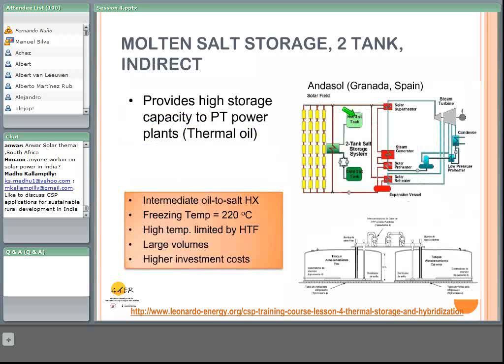You can see that it's a two-tank molten salt storage with a nitrate salt mixture, melting point of 223 degrees C, and a storage capacity of roughly 1 gigawatt-hour thermal, which in the case of a 50 megawatt plant is equivalent to 7.5 hours at full load operation. The storage tank size is 14 meters in height and 37 meters in diameter, and there are more than 27,000 tons of molten salts in the system.